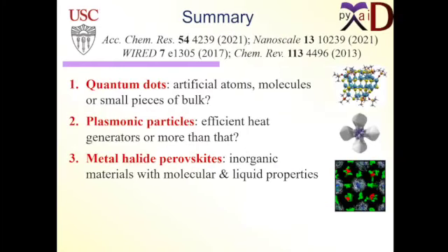So I think I'm going to conclude. What I talked about very briefly was the methodology we developed, which combines real-time TDDFT and non-adiabatic molecular dynamics. The goal is to model excited state dynamics following light excitation, or if you inject charges, you put a lot of energy, and everything happens very fast, on femtosecond, maybe not attosecond, but definitely femtosecond, picosecond, nanosecond timescales. And that's why we need these kinds of simulations. Everything depends on configuration. There's no approximation about weak coupling, such as people use for perturbation theory, Fermi's golden rule. So that's the value of the simulation.